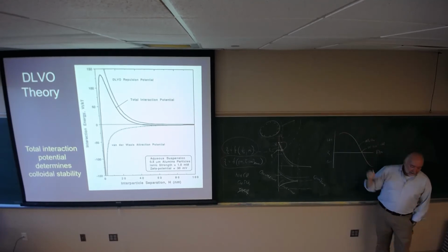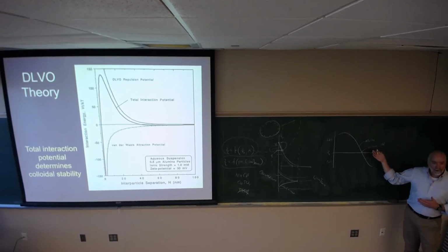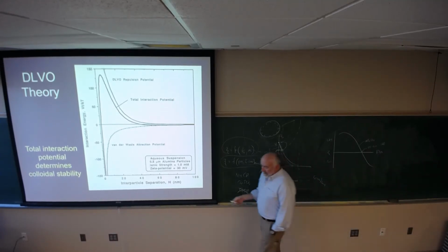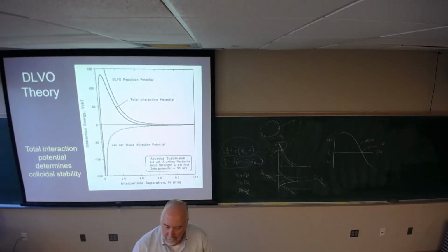The curve comes down because as I increase the concentration of acid, I'm bringing in other ions that are oppositely charged to the particle surface. So if I bring in HCl, for example, I'm increasing the concentration of chloride ions, and I have a positively charged surface. So I am building up counter ions in that system, and eventually I will start to compress the double layer. When I do that, my zeta potential will start to decrease.